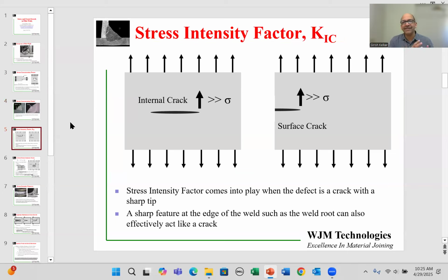Now, this is slightly different than the stress concentration factor in the sense that material properties also come into play once we are dealing with features which are like a crack, like a very, very fine separation between two components. So here I'm showing you a crack in schematic form in a component. This is an internal crack, so the entire crack is on the inside. You cannot see it from the outside. And the stress at the tip of the crack is going to be many, many times greater than the applied stress.